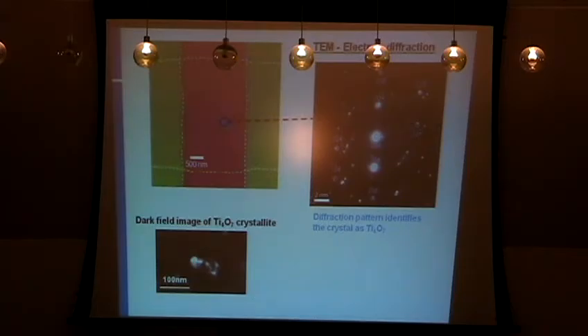Question about Magnéli phases: So the Magnéli system, there's a range of phases, that's right, and all of them have oxygen vacancies that are stable. And have you got any idea about the compositional distance and other elements? That's a good question. They each have a very distinct diffraction pattern, so we're actually seeing specifically Ti4O7. But why this one in particular? I think actually, as Stan had mentioned before, I think you can get a whole range of sub-oxides that are stable. It's a matter of the compliance current, how strongly we formed it. I mean, this occurred in the electroforming step.